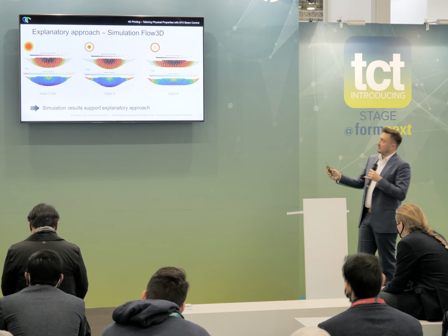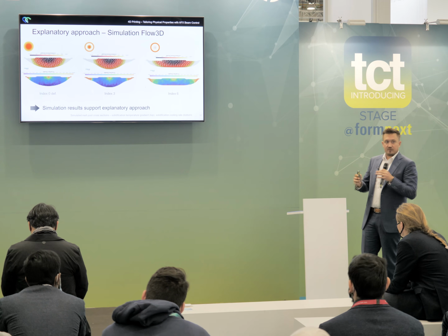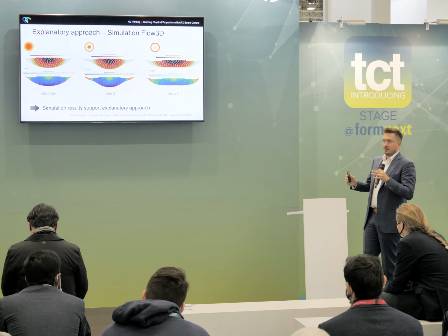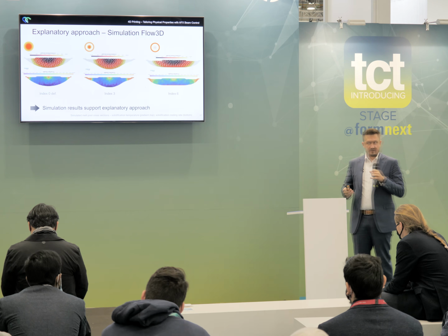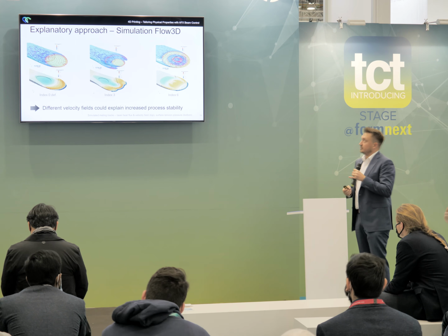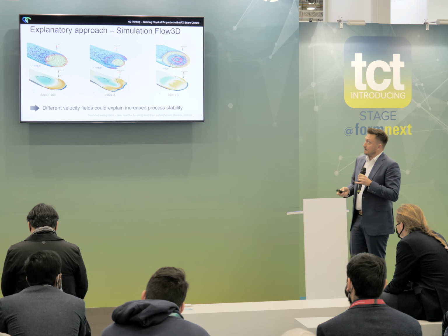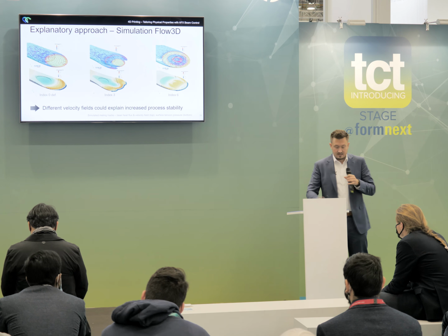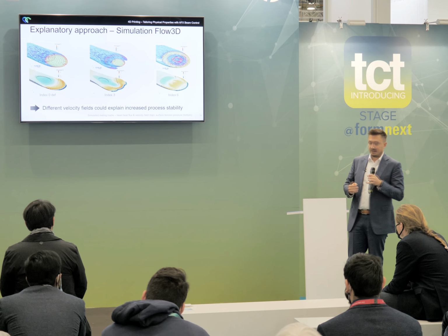And also in that case, we can clearly see that we have a large amount of parallel vectors, meaning a directed thermal gradient during the solidification. But there's actually a bit more going on, which was revealed by the simulation. In this chart, the vectors are the flow field or the velocity field of the melt pool dynamics.